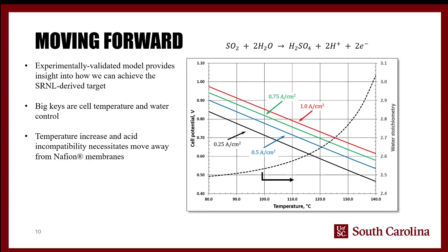If you hit 0.5 amps per square centimeter at 0.6 volts, but you're only producing 10 weight percent sulfuric acid, that's not sufficient. And so that's not going to cut it, and you have to be aware of that. And so what we find here is that we've got this experimentally validated model that Dr. Max Gorensek at Savannah River National Lab has been working on. So he's taken our experimental data and developed this model that lets us predict, choosing to fix certain parameters, what we need to be targeting to try and achieve our goal.